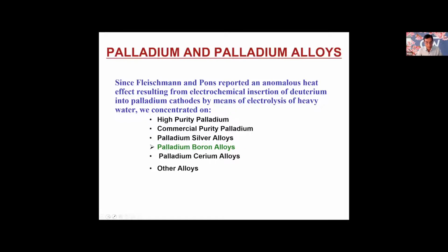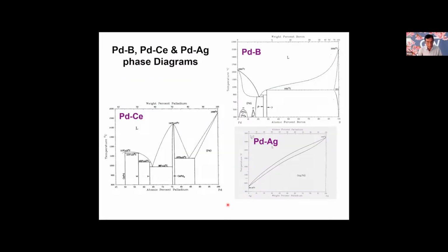So let's talk about the phase diagram. Here is the palladium cerium phase diagram. Here is the palladium boron phase diagram. And here is the palladium silver phase diagram. Just to be familiar with that, this is the atomic percent on the x-axis, and this is the temperature here. One thing here in the palladium boron alloy is we get a miscibility gap. What I mean is that if we put the boron into palladium in this region, the palladium breaks up, or dissociates, into two different phases, and I will discuss some more about that.